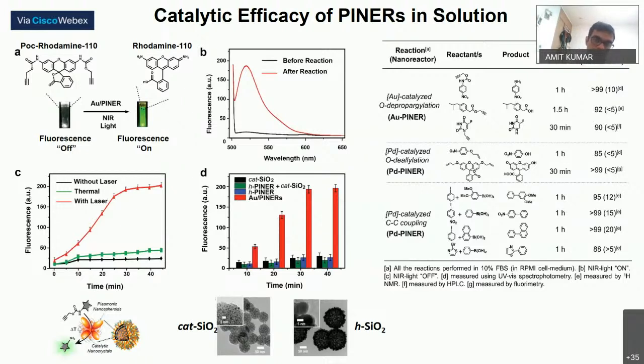So we tried to carry out this reaction only with the catalytic component of this nanoreactor, which is only the small nanocrystals. The conversion was very, very low. And we separately synthesized only the plasmonic component, hollow silica nanoparticles without any catalytic component inside, and we see very low reaction. So the large plasmonic nanocorona cannot catalyze this reaction. This reaction can only be carried out when the plasmonic corona is in close proximity with the catalytic component.